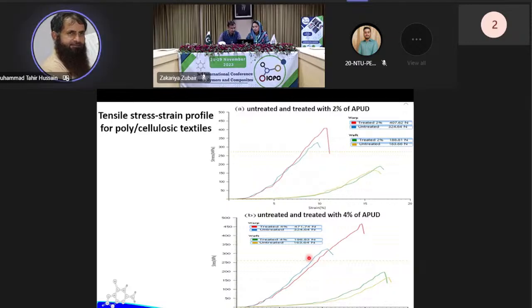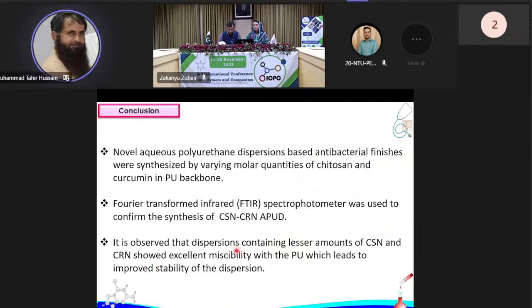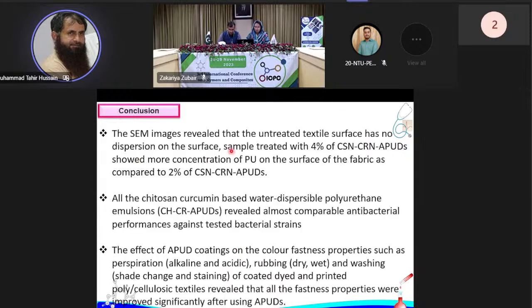Conclusions. In this research work, novel aqueous polyurethane dispersion based antimicrobial finishes were synthesized by varying the molar quantities of chitosan and curcumin in the PU backbone, and FTIR confirmed the structure of our material. It was observed that containing lesser amounts of chitosan and curcumin showed excellent miscibility with the PU, which leads to improved stability of the dispersion. The SEM images revealed that the untreated textile surface has no dispersion on the surface, and the sample treated with 4% dispersion showed more concentration of PU on the surface of the fabric as compared to the 2% finish.